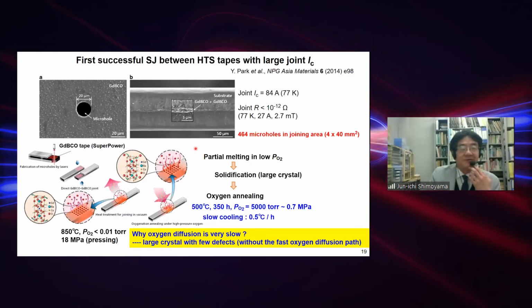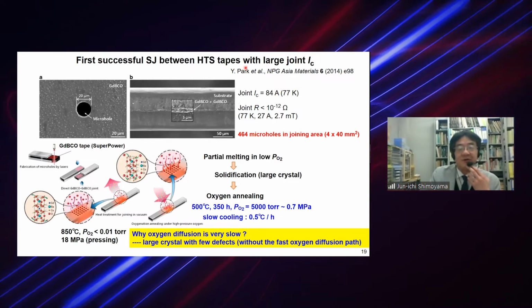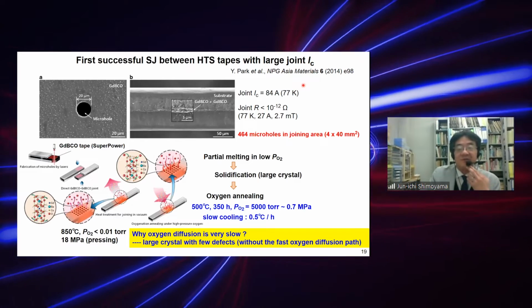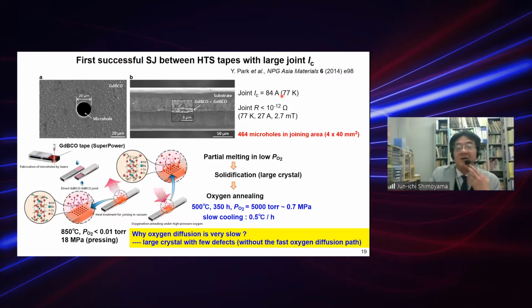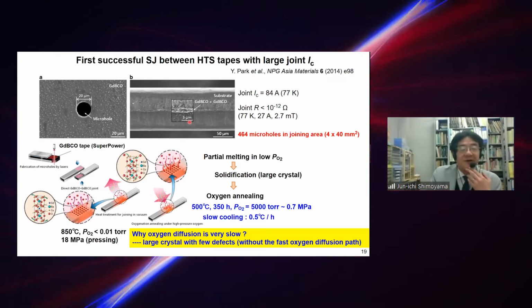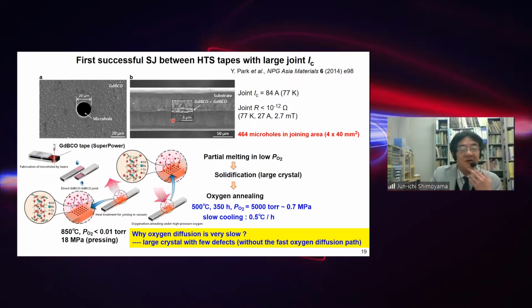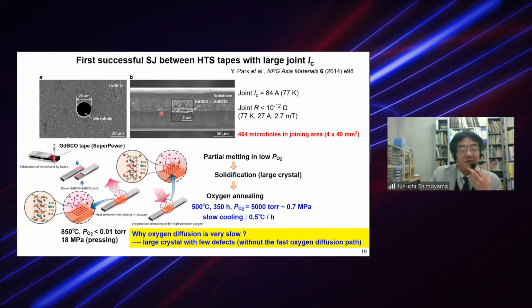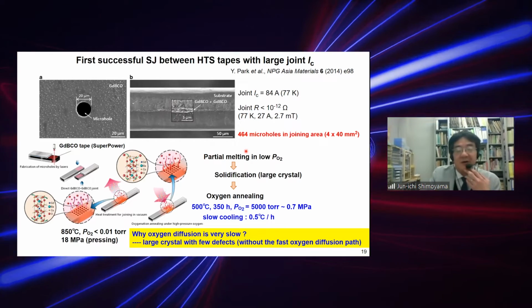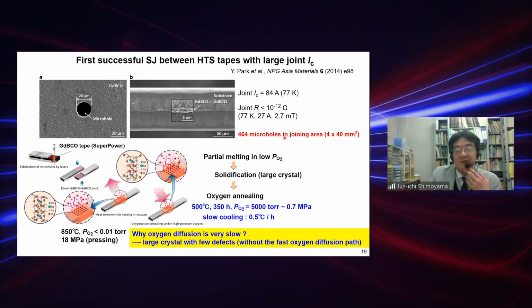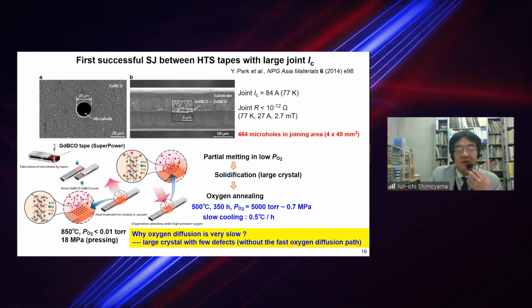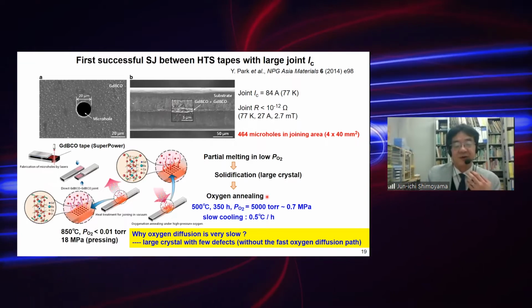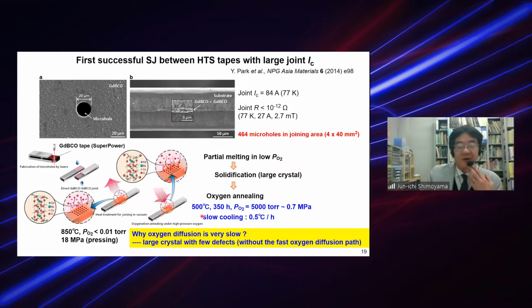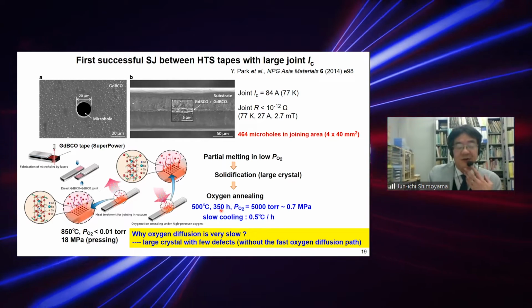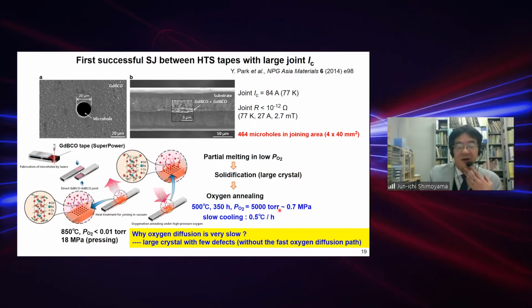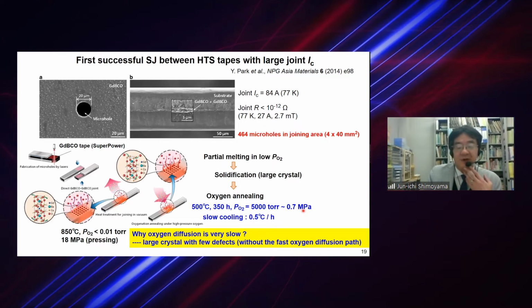So this is the first successful superconducting joint between HTS tapes with large joint IC. This report was published 7 years ago. They prepared a GdBCO joint by melt solidification. Gadolinium 1 to 3 tapes are connected in this way by melt solidification. However, they must make 464 microholes in the joining area to introduce oxygen after melt solidification. In their method, they applied oxygen annealing at 500 degrees C for 350 hours at a relatively high oxygen pressure, 0.7 megapascals.